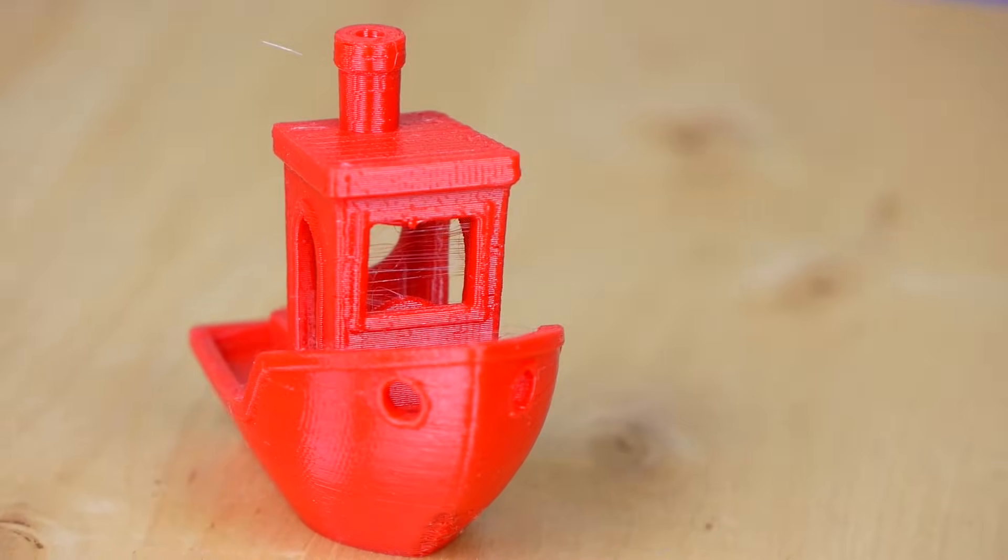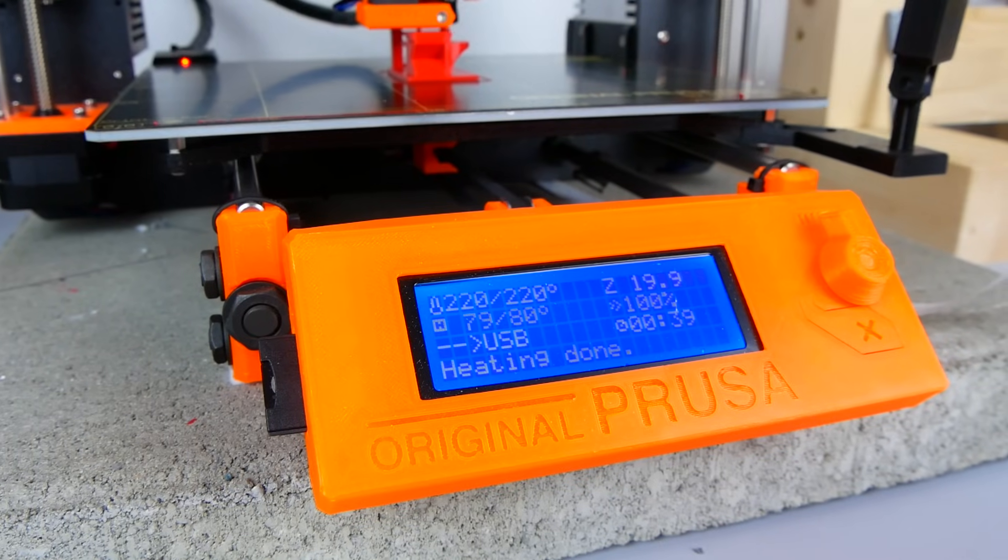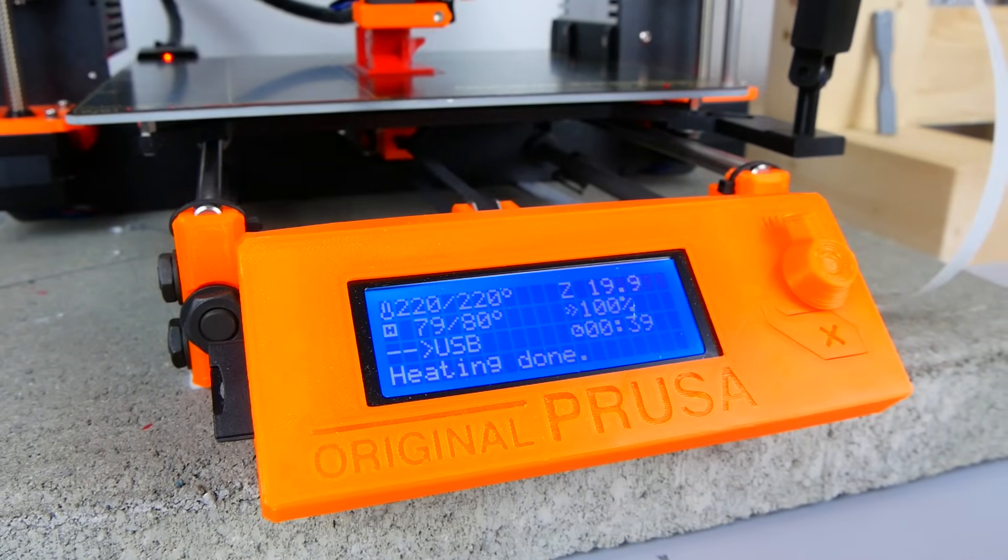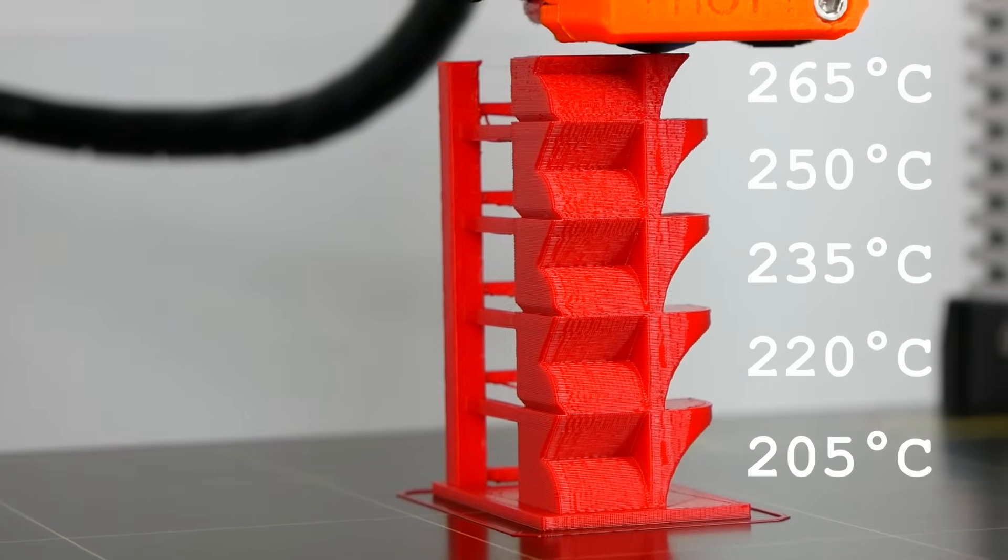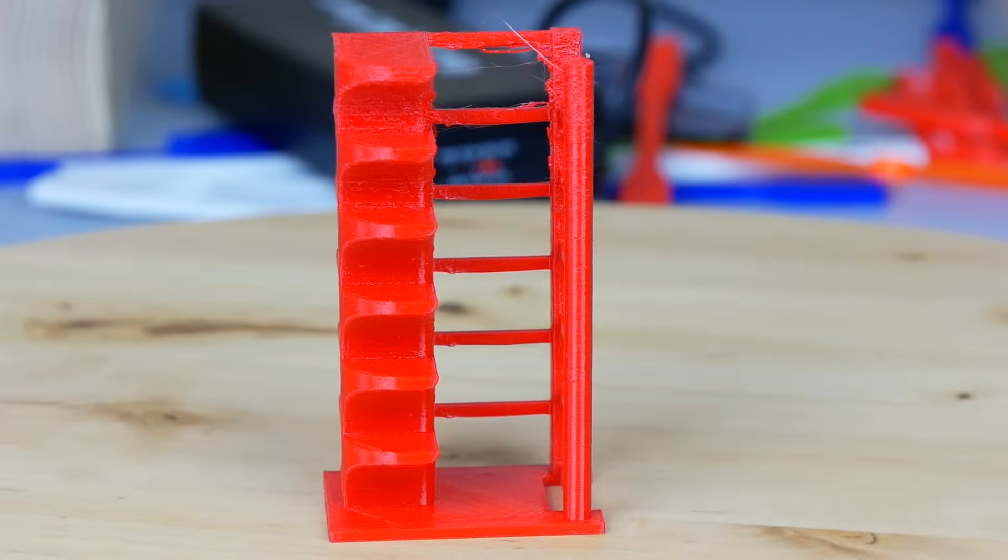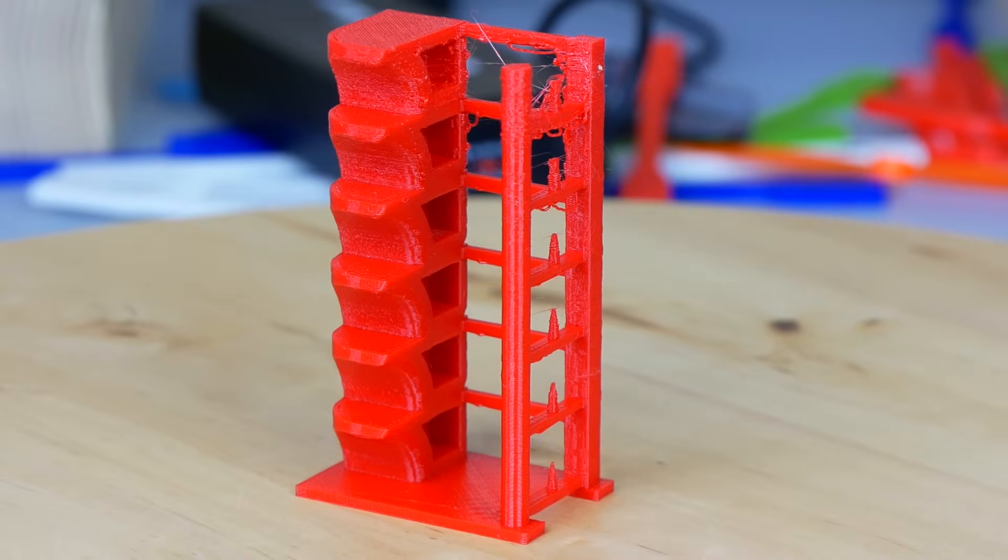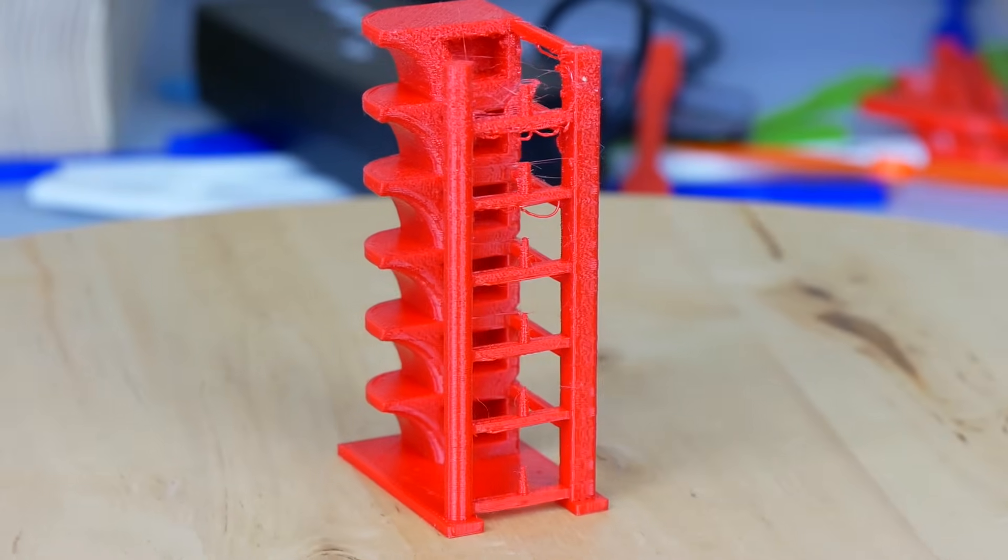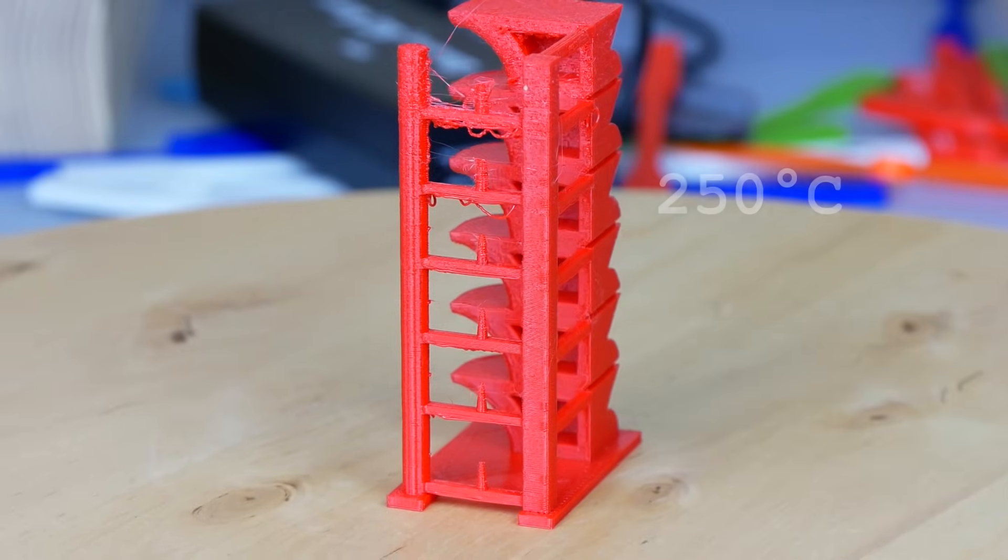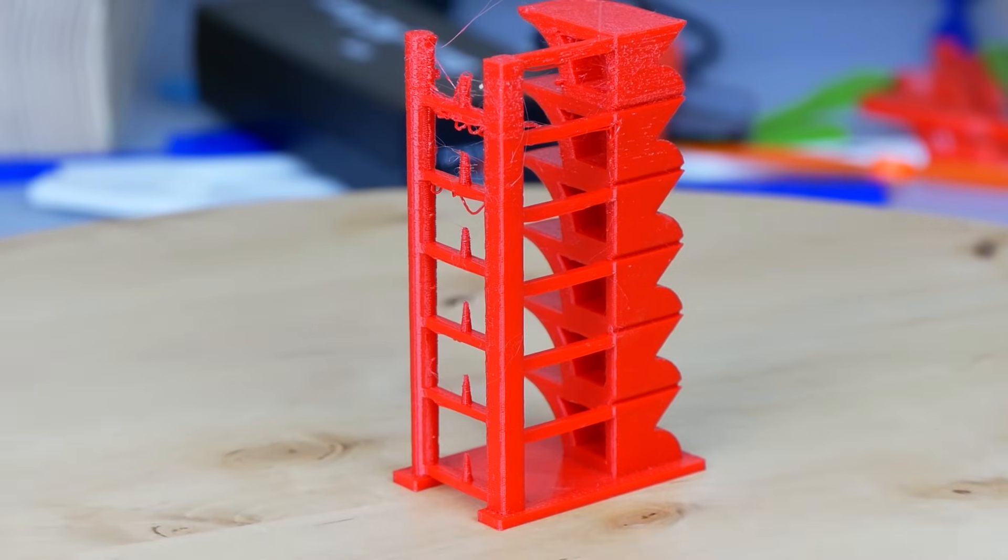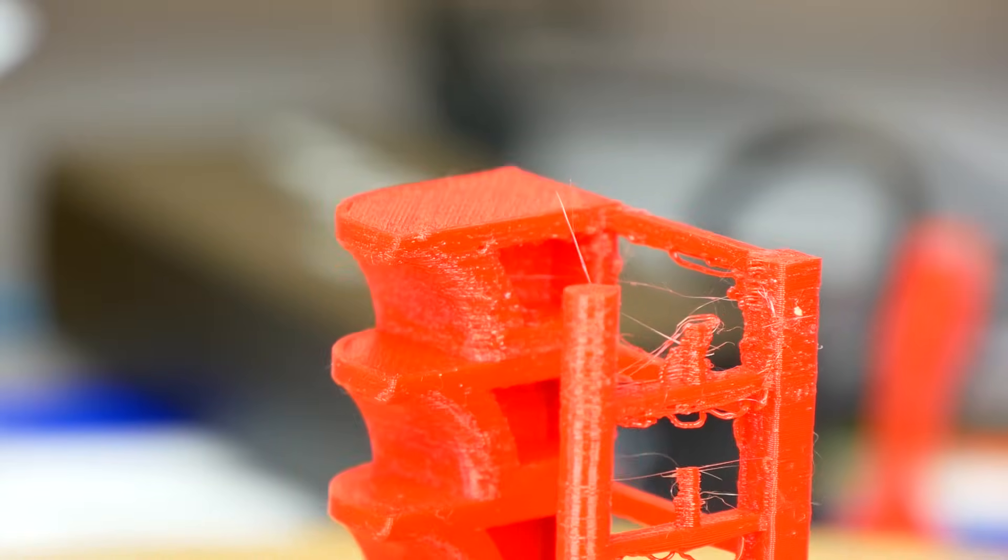So now to the temperature test. As a start, I wanted to find out what the temperature range of my PETG was, so I printed out one of these temperature towers with values from 205 degrees to 280 degrees Celsius. We can see that the print did not fail at any of these temperatures. Still, the quality really starts to degenerate at higher temperatures. The results seemed to be okay up to 250 degrees, at which point you see quite a lot of bubbles forming in the print. Also the stringiness increases constantly. Overhangs printed very well, all the way up to 280 degrees Celsius.